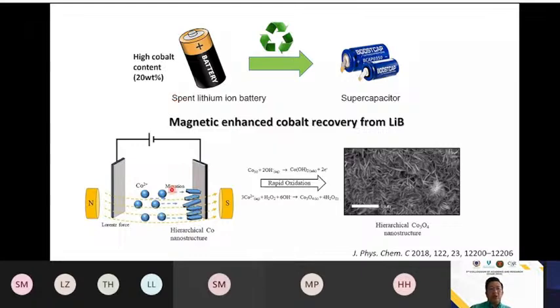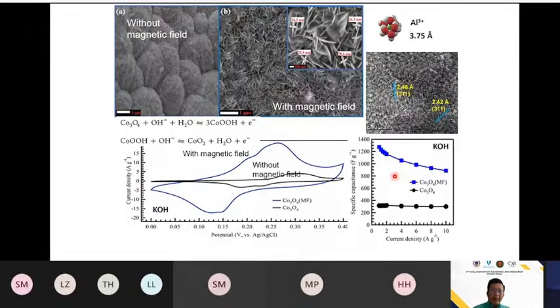We run through the electrochemical treatment as well. In this case, we enhance it with the magnetic field, because cobalt actually has a magnetic nature. And then we see that it can form a very nice structure of this cobalt oxide. Again, we compare it without the magnetic field. We can see that we can form a very nice structure with this magnetic field. And we run the cyclic voltammetry as well. We can get a very nice, very high charge storage.